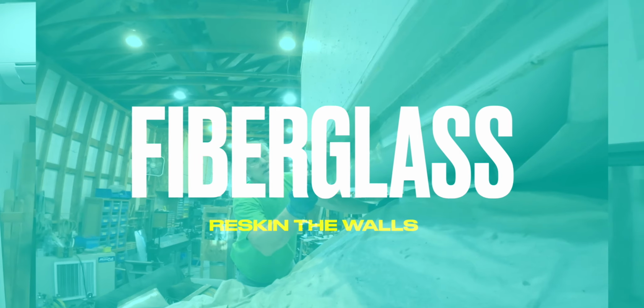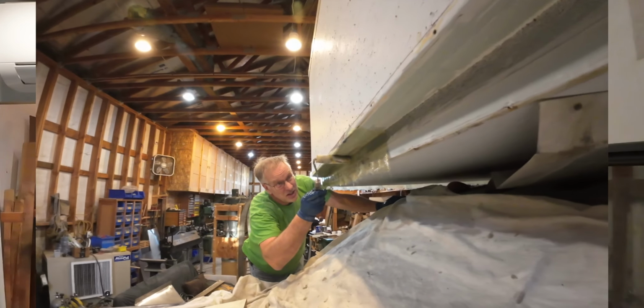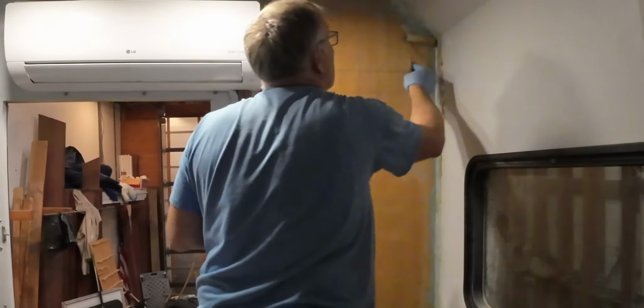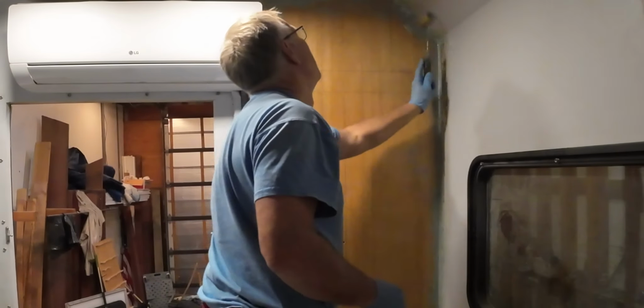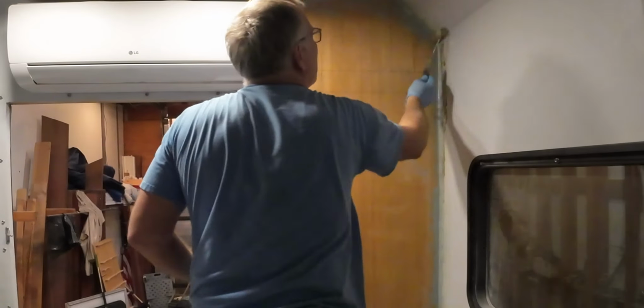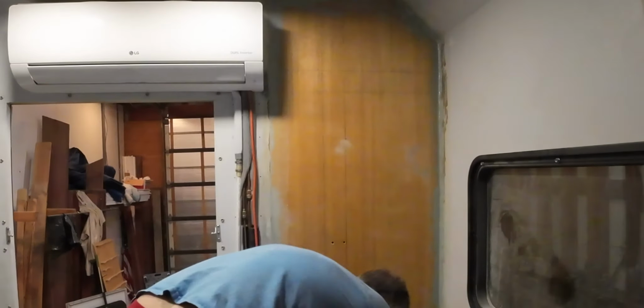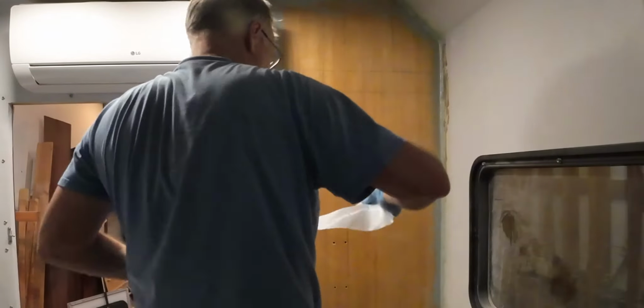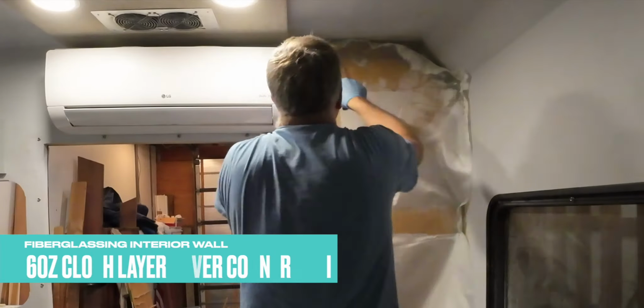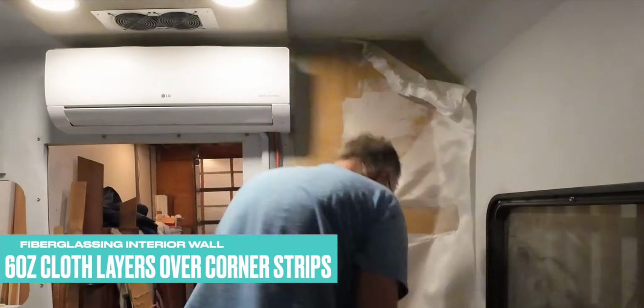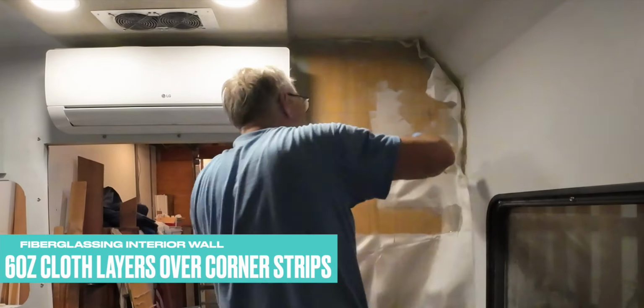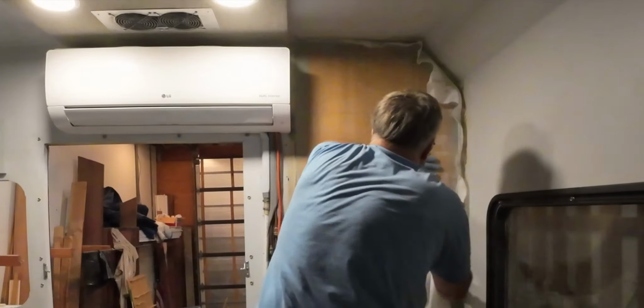The exterior corners were covered with 1708 cloth, providing structural support without the concern of cosmetics. However, the interior wall joint steps are slightly different. To keep a smooth transition between the new back wall and the existing side wall, the process involved first filling the corner with putty, then sanding to a smooth radius. Then, using all 6-ounce fiberglass cloth, multiple layers are applied. First, a 6-inch strip was applied and cured, followed by a 4-inch strip, and then finally the full wall covering is applied, which overlapped the corner strips. Being a lighter material allowed Steve to then sand the edges and create a smooth transition at the wall.